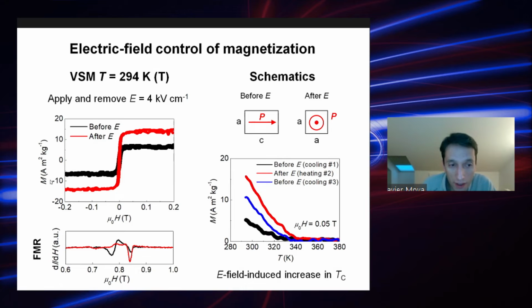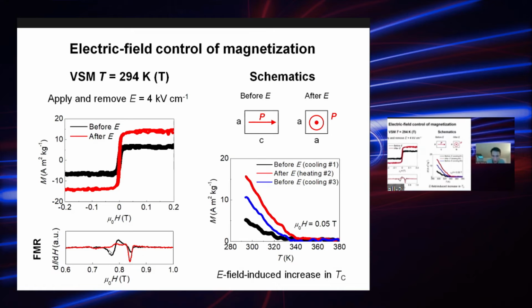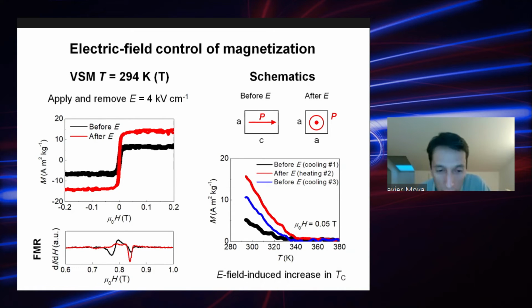You can see this using magnetization and magnetometry. You can also see this in ferromagnetic resonance, where initially you have two peaks and then you have only one. And this is pointing to the fact that before applying field, you have two different regions of magnetization in the film. So you have two different resonance peaks. And when you apply the electric field, you convert one of the regions into the other. So this is why these peaks disappear and this peak increases. And I'll tell you in a second why is this.